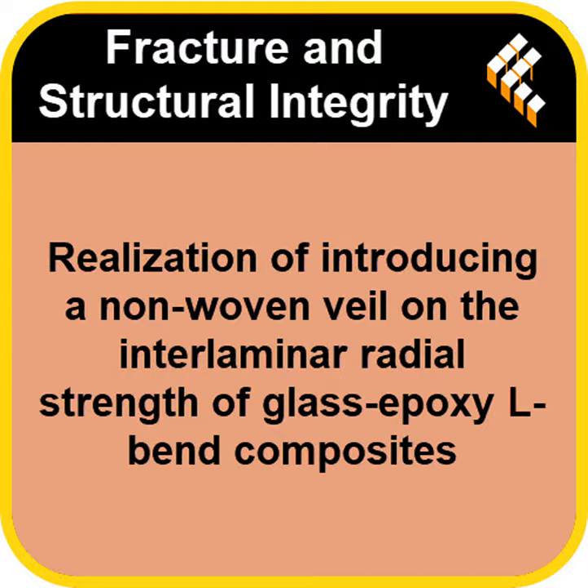No, and that's what makes this comparison so interesting. Glass fibers are much less stiff than carbon, lower modulus. They tested two densities, 25 and 30 g/m². And what happened as they increased the density for glass? The trend completely flipped. With the glass veils, the load carrying capacity and the curved beam strength actually improved slightly as the density went up from 25 to 30 g/m². So more glass helped a bit. It did. The 30 g/m² glass veil sample achieved the best result for glass, getting about a 17% improvement in CBS over the baseline sample with no veil. Okay, 17%. It's an improvement, but nowhere near the 88% boost we saw with the low-density carbon. Not even close. But the key point is the trend. For glass, adding more material didn't cause that catastrophic drop-off in performance. It actually helped, albeit modestly.